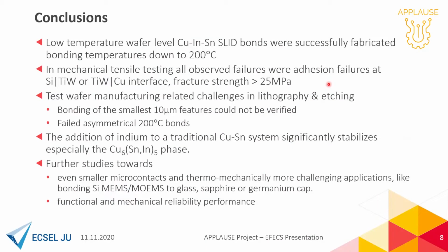So to conclude, low temperature wafer level copper-tin indium SLID bonds were successfully fabricated, bonding temperatures down to 200 degrees centigrade. In mechanical tensile testing, we didn't observe any failures which would propagate through the actual interconnections. All failures were adhesion failures at either silicon titanium-tungsten or titanium-tungsten copper interface, and the fracture strength were higher than 25 megapascals. We still had some test wafer manufacturing related challenges in our lithography and etching processes that caused that the bonding of the smallest 10 micrometer features could not be verified. In addition, the asymmetrical 200 degrees centigrade bonds failed.